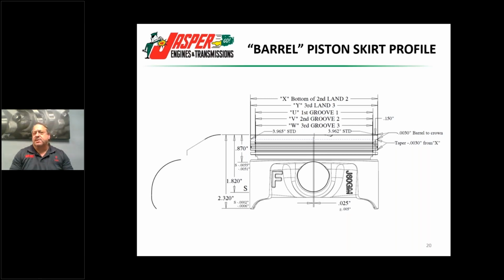Yes, what you don't want to do is see something that's flaked off. One of the biggest problems encountered with EPA probably about 10 years ago: some of the cleaners used to clean the pistons and really get them clean before coating were basically outlawed. So some of the cleaners they're using these days don't get them as clean. If anything flakes off, that is due to the piston not being clean, not getting all the oil and residue off before it was coated.